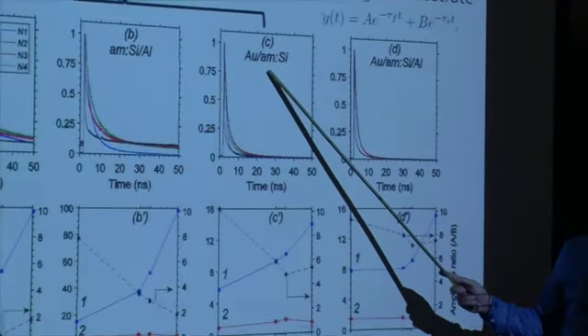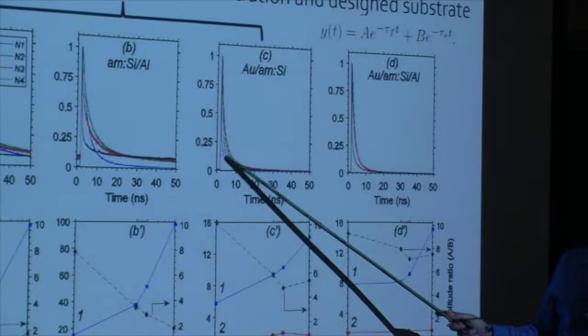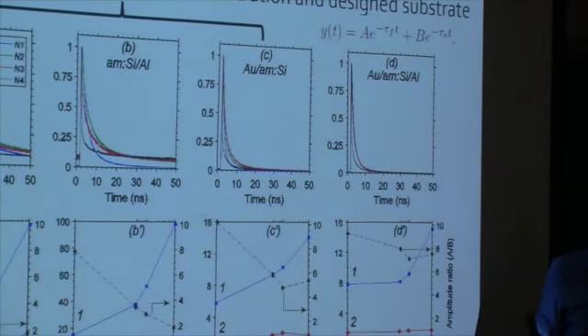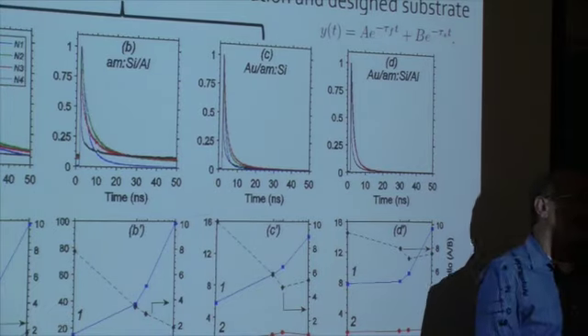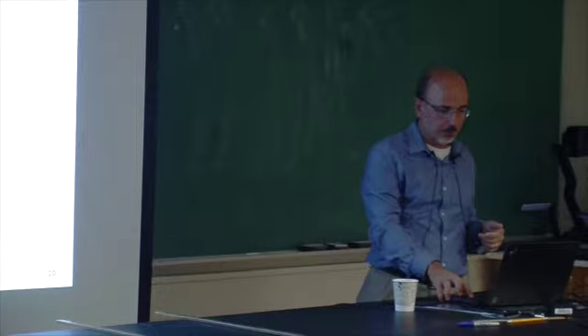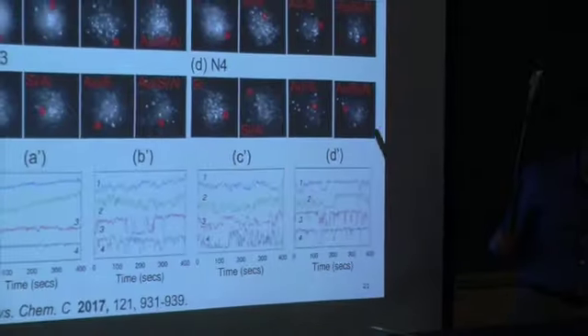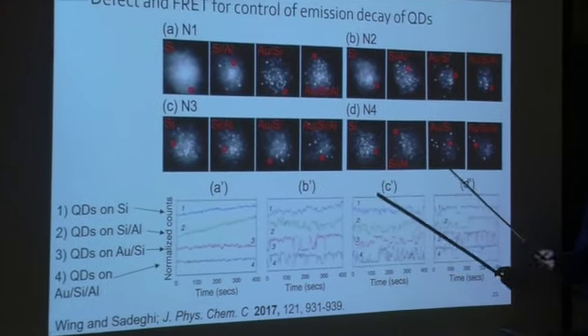Then if you go with the gold, you can see everything becomes faster. Every one of them becomes faster. The reason is that Förster transfer takes care of it: the quantum dot on top has the chance of giving up its energy to the metallic nanoparticle too. So that's why it makes it faster. I'm making this a little bit short because I want to touch on the other subject. But let me show this, what I was going to talk about is important.